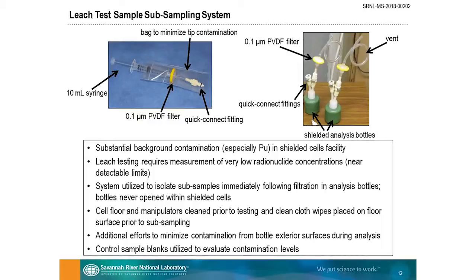Another issue in the facility is this facility is many decades old. It's had lots of different types of samples come through. Contamination is an issue, and the concentrations we expected to see were very near our detection limits analytically. So it was a challenge to analyze these samples and avoid contamination and prove to ourselves that we did not have contamination. So substantial background, especially for plutonium.